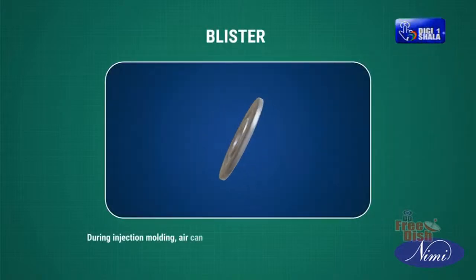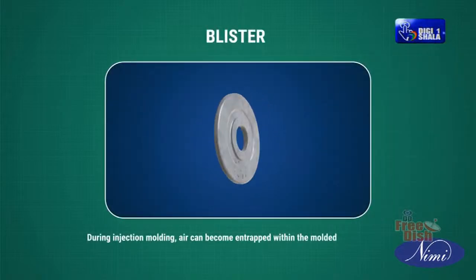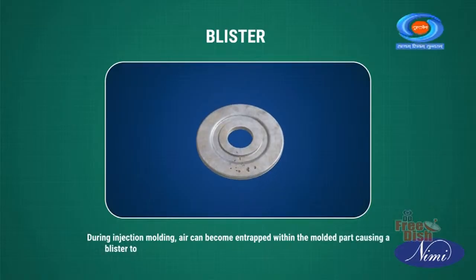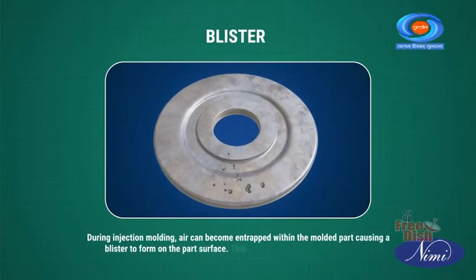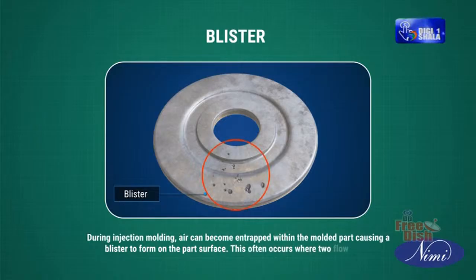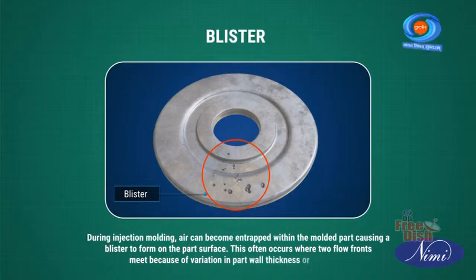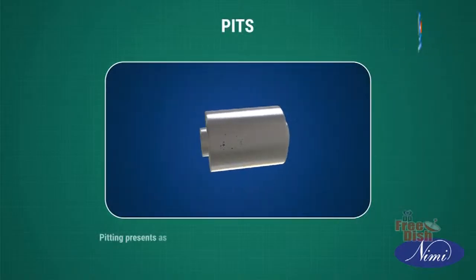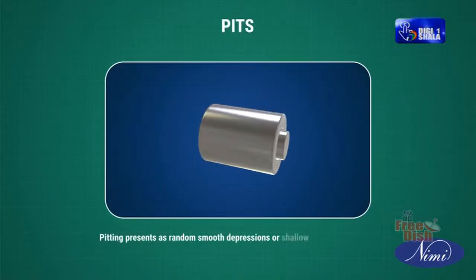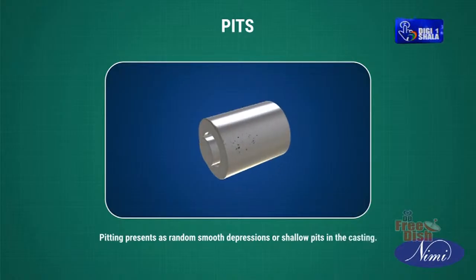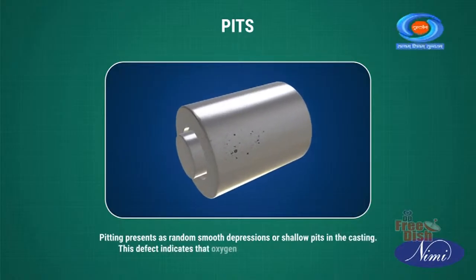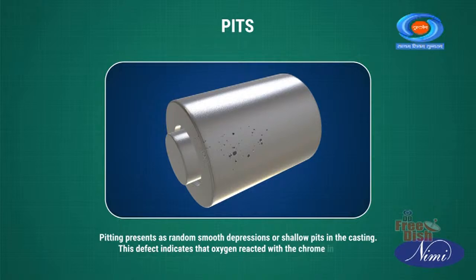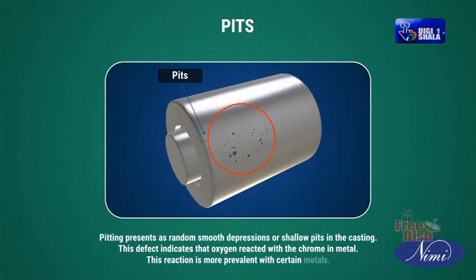Blister. During injection molding, air can become entrapped within the molded part, causing a blister to form on the part surface. This often occurs where two flow fronts meet because of variation in part wall thickness or geometry. Pits. Pitting presents as random smooth depressions or shallow pits in the casting. This defect indicates that oxygen reacted with the chrome in the metal. This reaction is more prevalent with certain metals.